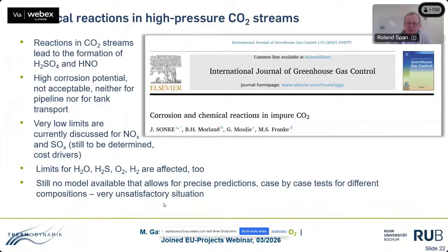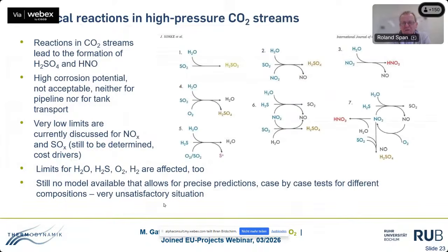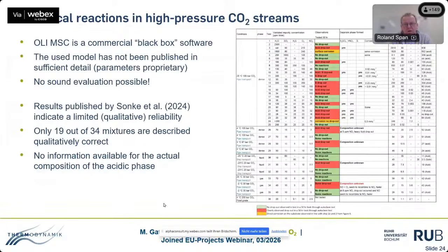And these reactions, in the end, all lead to the formation either of sulfuric acid or of nitric acid. And sulfuric acid in particular forms, together with water, a second highly corrosive phase at concentrations which are much lower than the concentrations we have for the condensation of pure water. Now, IFE in Norway has run extensive, very complicated tests to see where we find dropout of a second phase and where corrosion becomes visible.